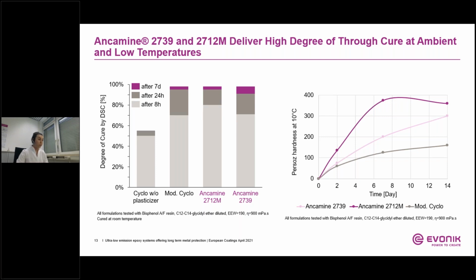In the absence of plasticizer, the reaction with cycloaliphatics would stop after 24 hours, and full curing cannot be achieved. This demonstrates clearly that the cycloaliphatics need such a high level of plasticizer for a through cure at ambient to build their properties.